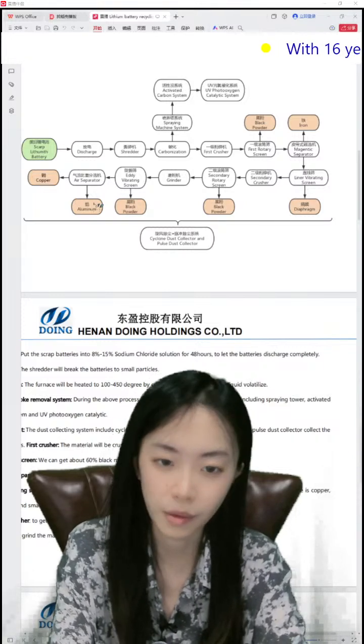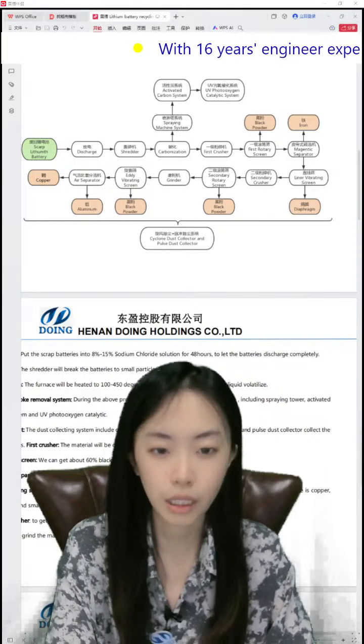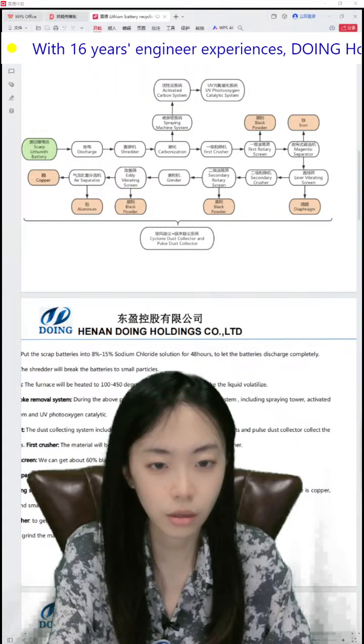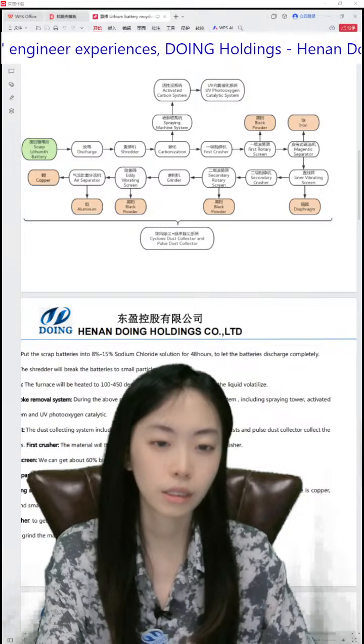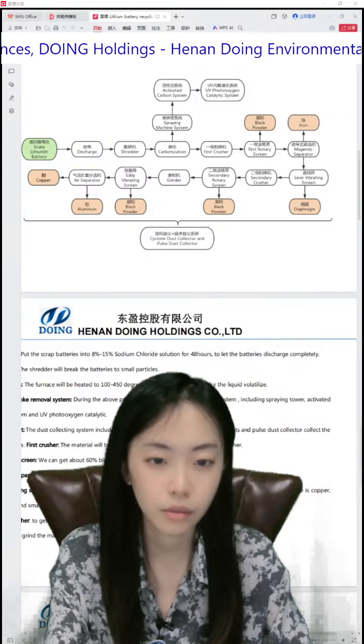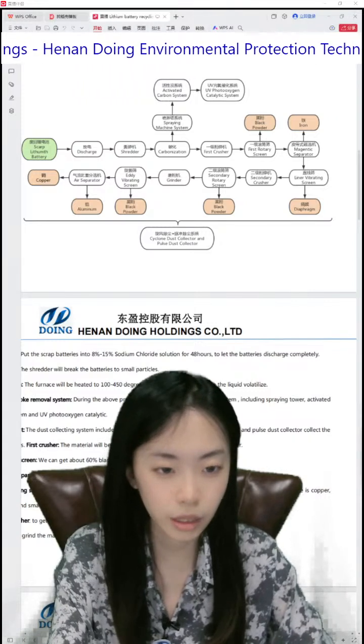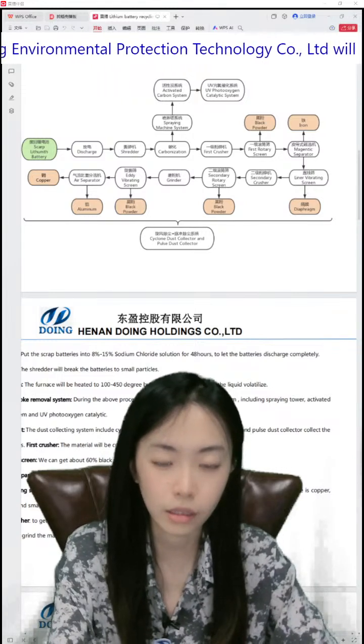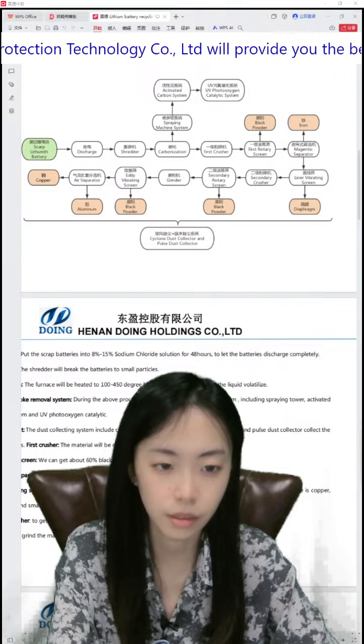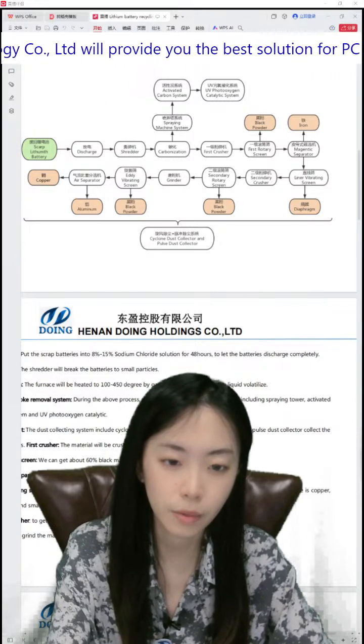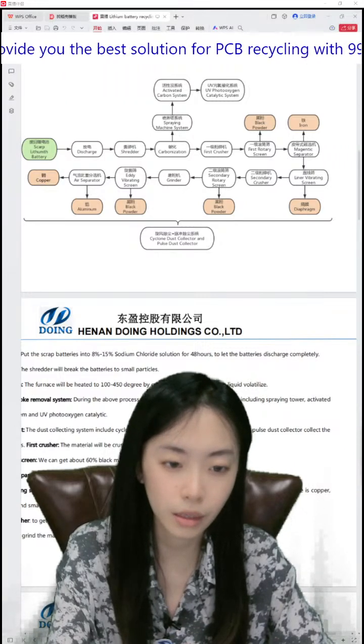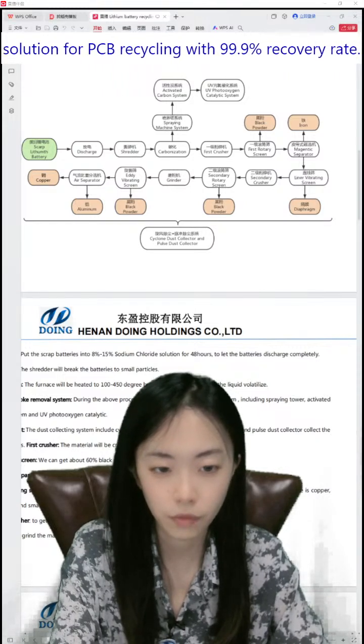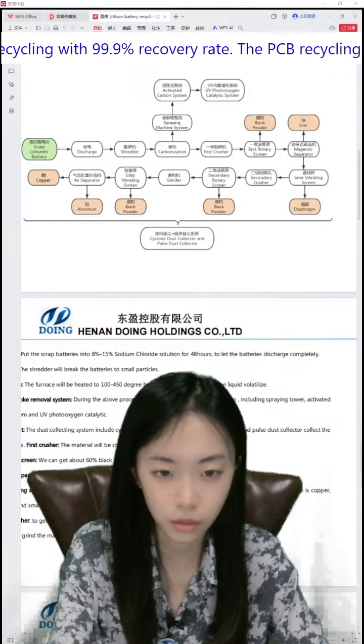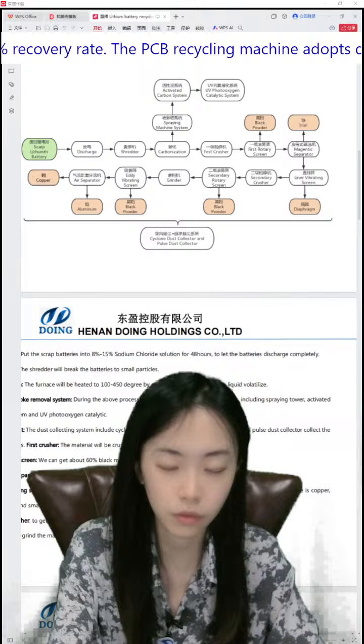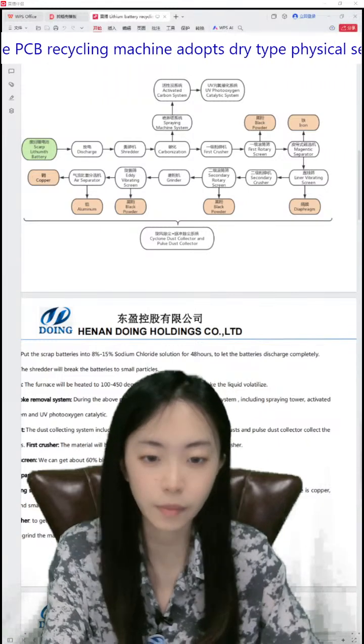And then the last raw materials are the metals, the copper and the aluminium. So we will use the air separator, because the two kinds are both metals, so we can't use the electrostatic separator. We can use the air separator. We'll sort the material by airflow and vibration friction on the raw materials. So the larger copper particles will settle to the bottom, and the smaller aluminium particles are suspended on the surface of the material layer by the action of the airflow. So in this link, the recovery rate of the copper and the aluminium is about 98%.